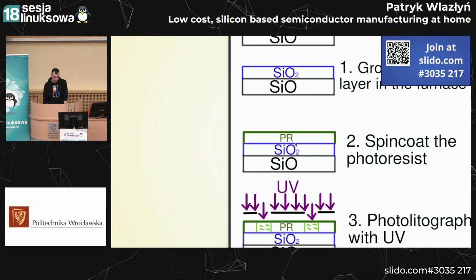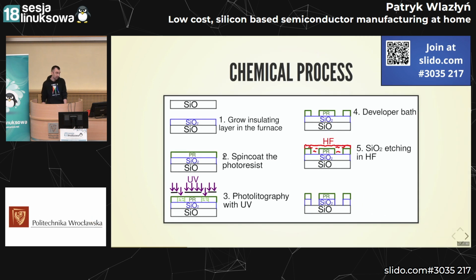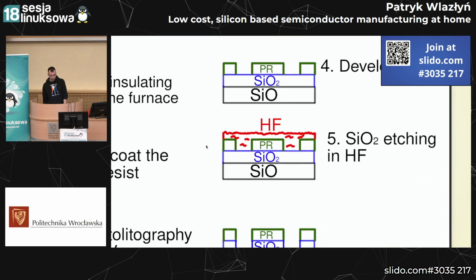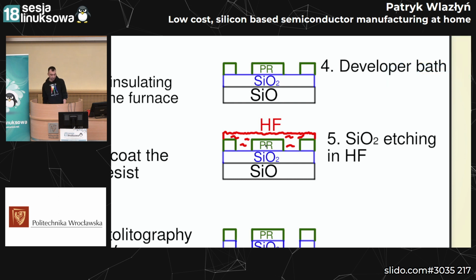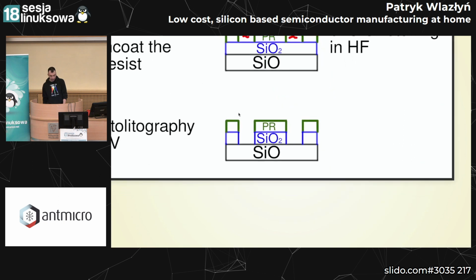Then we spin something called photoresist, and it is a chemical substance, usually a liquid, that you can put on a wafer, and when you shine a light on its photoresist, you will be able to wash it out later, basically creating these openings in the wafer, and these openings can later be used with another chemistry like HF to etch the silicon dioxide, and we will get something like this.